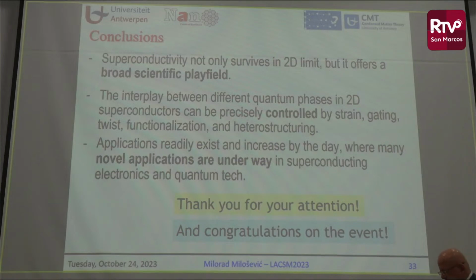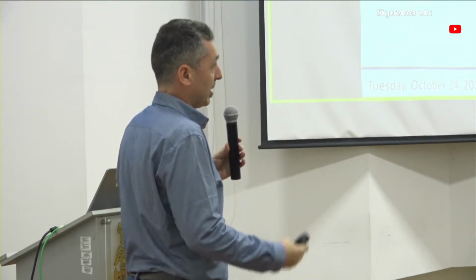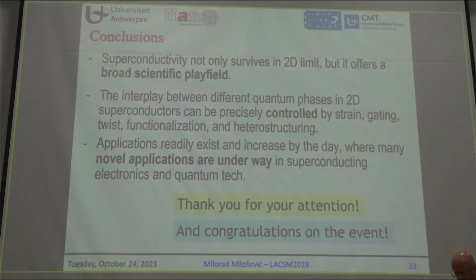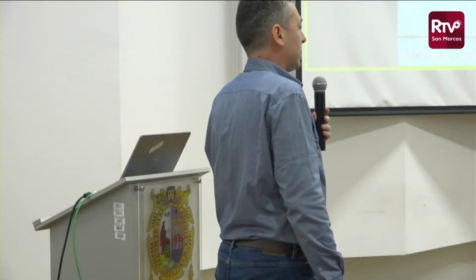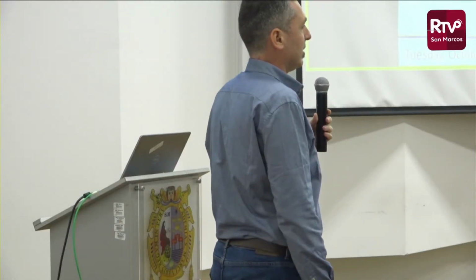From a computational point of view, first of all, this is a very old story. Already Ashcroft has shown that metallic hydrogen would be metallic and then superconducting as we increase the pressure. It would be superconducting up to 400 Kelvin. Similar calculations for hydrogen have been done from first principles by Pickard and company also years ago. So there's little doubt that this conventional electron-phonon coupling can indeed lead to this high temperature. So that's not really under question here. However, what has been done in experiment doesn't seem to correspond to what the theory predicts.